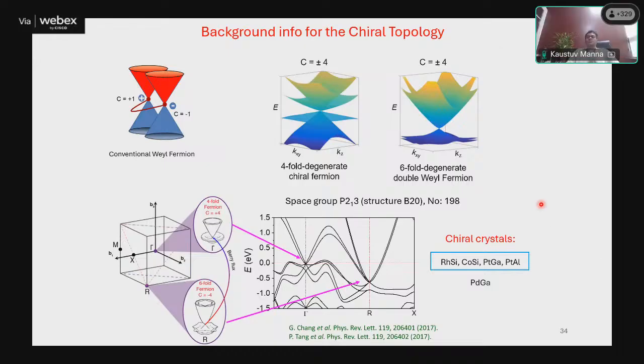Okay, so what this 2017 paper says is that at high-symmetry points like the gamma point and R point, you can have this multifold band crossing which is protected by Kramers degeneracy. So these are Kramers Weyl points. Why Kramers Weyl points? Because time reversal symmetry is protected. These are the time-reversal invariant momenta points, gamma and R.